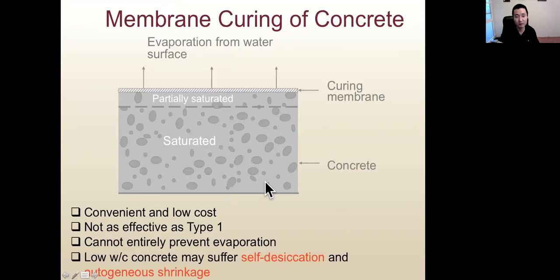So the second type, sealing the concrete, is okay, but is not as good as the first type because not every part of the concrete is saturated. By putting plastic sheets or curing compound, part of the concrete is saturated, but the part of the concrete near air is only partially saturated. That means the hydration here may not be fully developed.